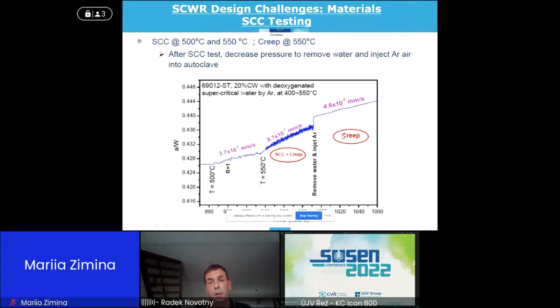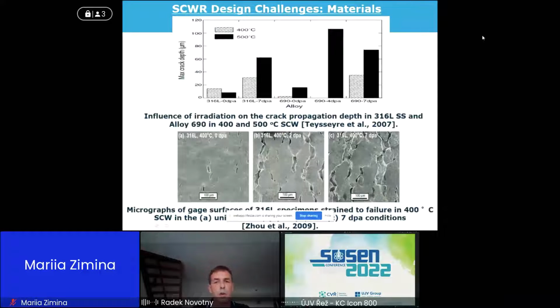and that means the SCC mechanism changed during the test, changing the conditions of this test to creep. So we can also expect, at such high temperatures and for this material, the effect of creep. So in any case, this is a big gap in our research, and we need many more experimental results to actually get enough data and evaluate this.